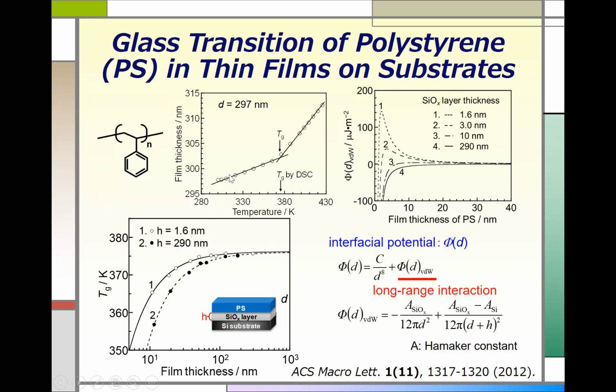And see, with increasing temperature, thickness is going to increase as well, because we have to think about the thermal expansion. But with increasing temperature, when we reach a special temperature, this slope changes because we reach the glass transition temperature. So by measuring the temperature dependence of thickness, we are able to determine the glass transition temperature of this kind of thin film. That's what I'm talking about.